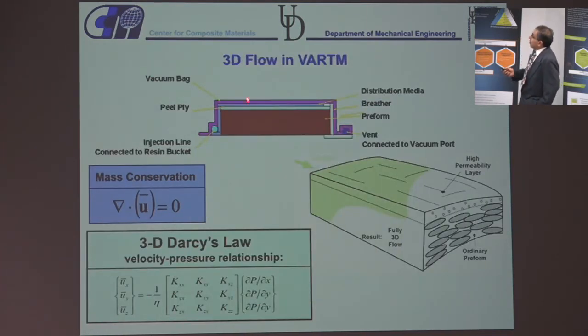Now, of course, you can extend that to 3D, and then instead of having to deal with 4 values, you have 9 values to deal with. The nice thing is that, well, we have proved this is a symmetric tensor, so you only have 6 values to worry about that you have to calculate. And the reason you need to solve 3D in VARTM is because usually in VARTM you put a distribution media on top, which allows the resin to go faster on the top, and so in reality through the thickness you have a 3D flow, so that's why you need to solve it as 3D. In RTM usually that is not present, so you can do it as a 2D problem.